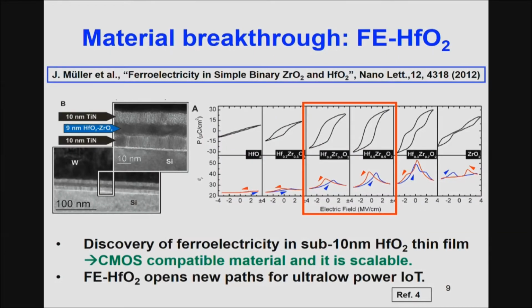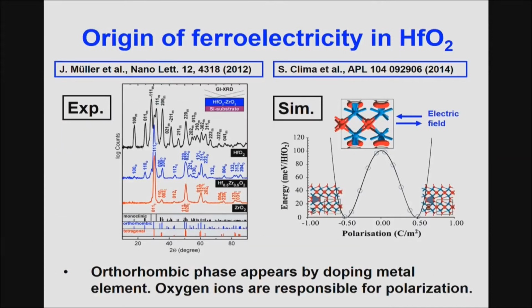But luckily, recently ferroelectricity has been discovered in hafnium oxide thin film, which is already used in CMOS technology, and it's already mature. What's good for this material is it shows ferroelectricity at less than 10 nanometers. It's really thin. And you can use a very typical ordinary metal electrode like titanium nitride or tantalum nitride, so it's easy to pattern. So this material is CMOS compatible and scalable. I believe this material will open a new path for ultra low power logic and memory applications. So that's the key idea.